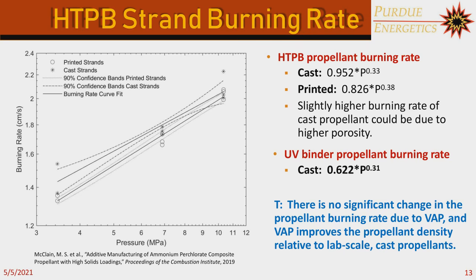And we have our burning rate curve fits here. So if you recall, the formula for the burning rate curve fit is a times P to the n. Essentially, n is our pressure exponent, and a is our pressure coefficient. The coefficient tells you how offset these curves are, and the pressure exponent tells you the slope of these curves. So as we can see, there's not a lot of significant differences between the two.